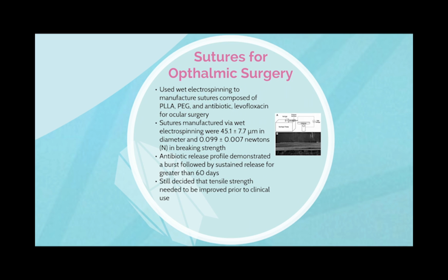Now, there's also sutures for ocular surgery. In this, they actually used wet electrospinning to manufacture sutures composed of PLLA, PEG, and the antibiotic levofloxacin. The sutures were manufactured in wet electrospinning. They were actually found to be 45.1 plus or minus 7.7 micrometers in diameter and had a 0.099 plus or minus 0.007 newtons in breaking strength.